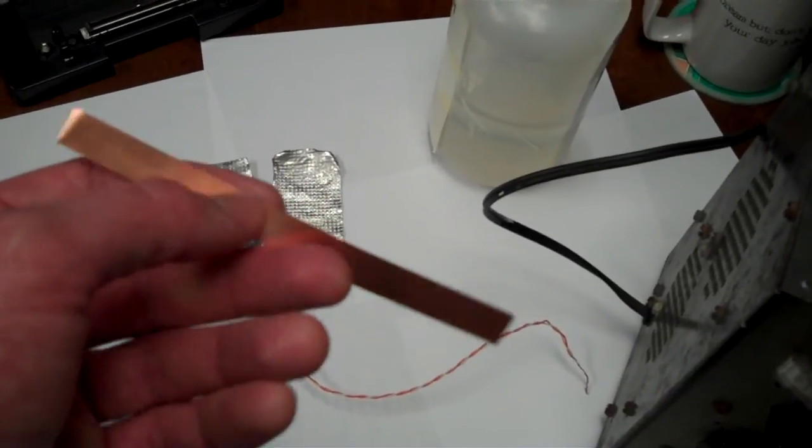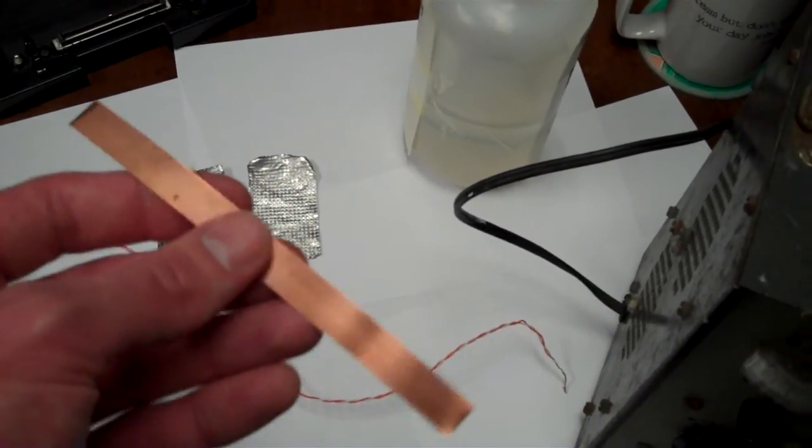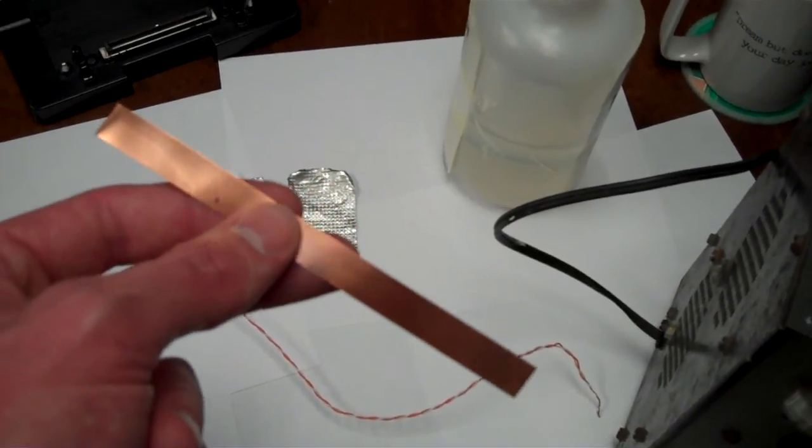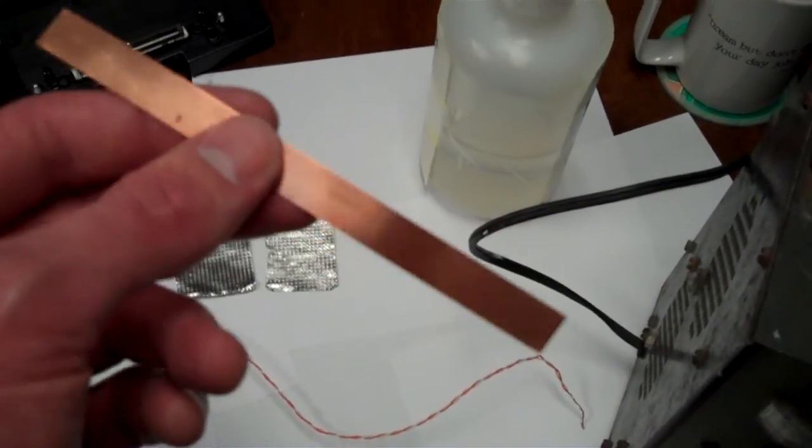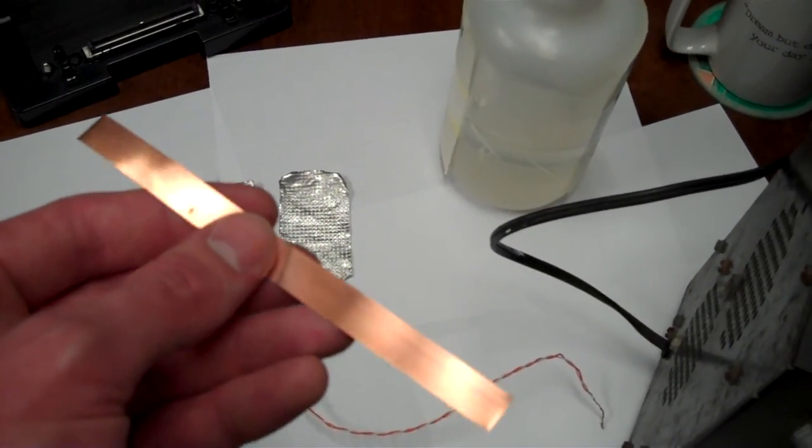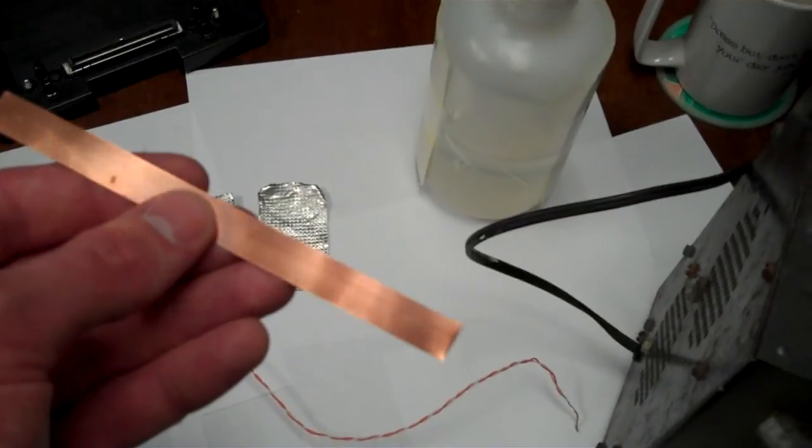If the material is not clean, is not free of oxides, the indium may plate onto it and it may be kind of deceiving, because you'll physically see the indium on there, but it may not adhere very well. And that's why pre-treatment of some metals is necessary.